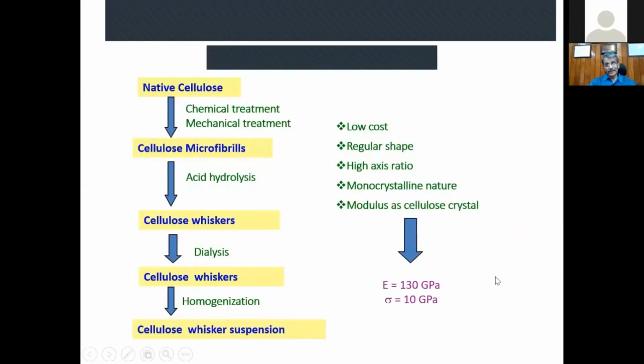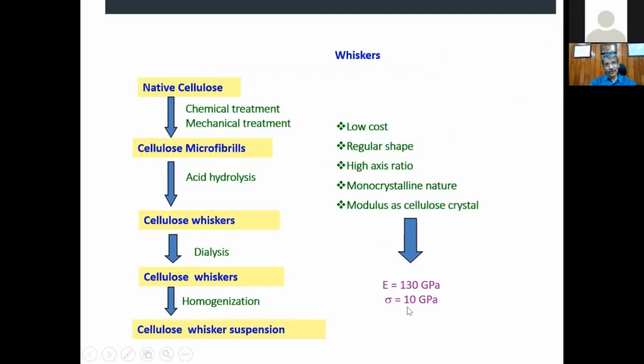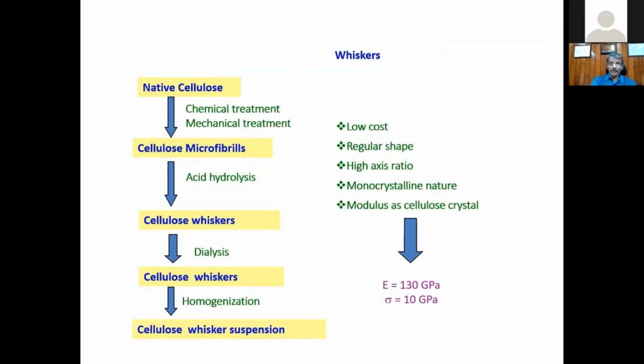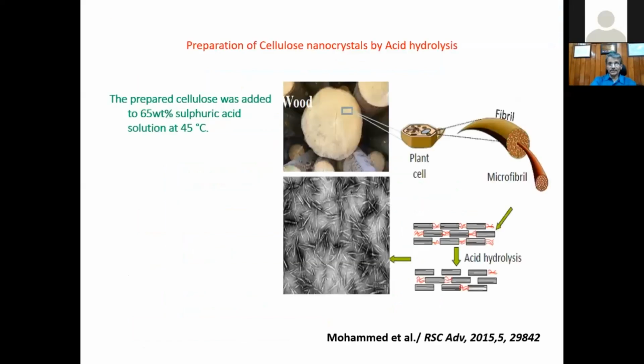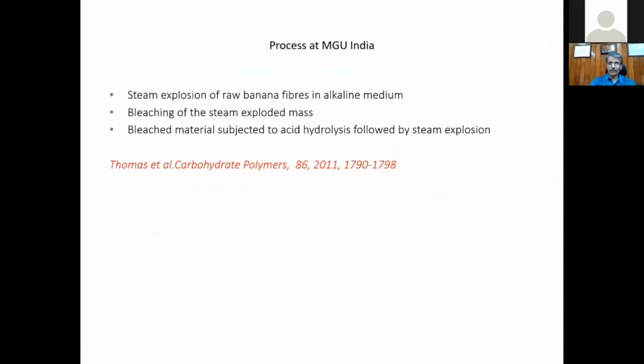Dear friends, nanocellulose has a very high modulus, close to 130 gigapascals, and very high strength. A typical polymer modulus is maybe 2 or 3 gigapascals. So nanocellulose offers high modulus and high strength. Look at nanocrystals made by Mohammed and group from wood flour. Mohammed used strong sulfuric acid, 65% sulfuric acid, starting from this wood flour.